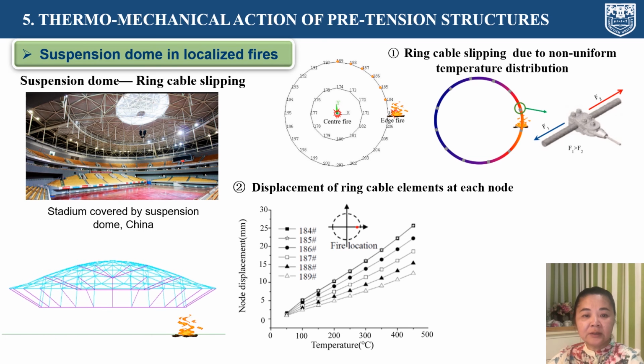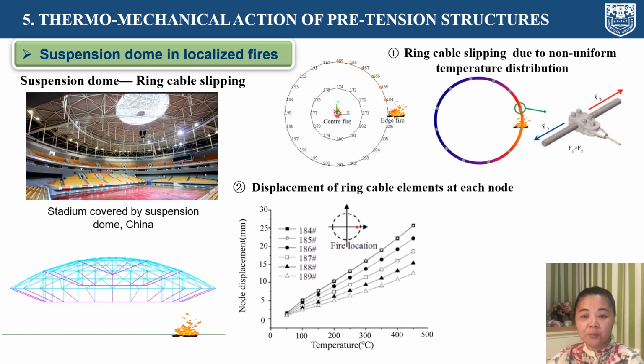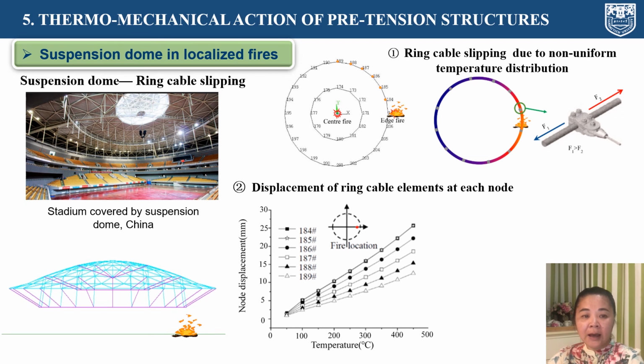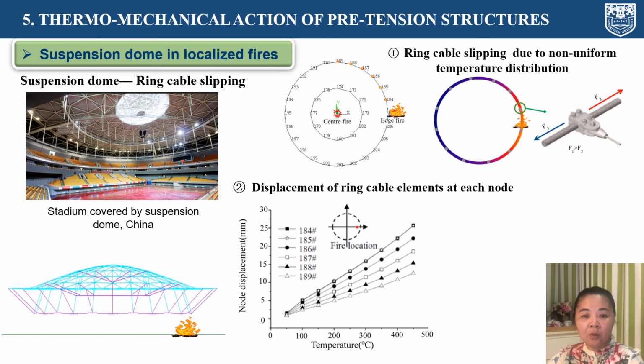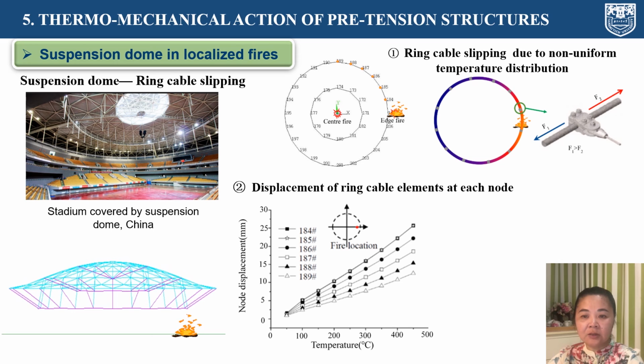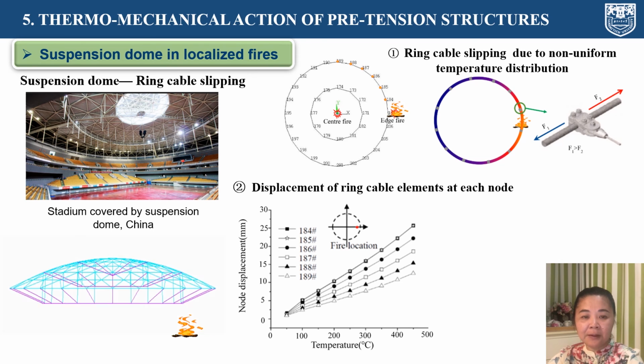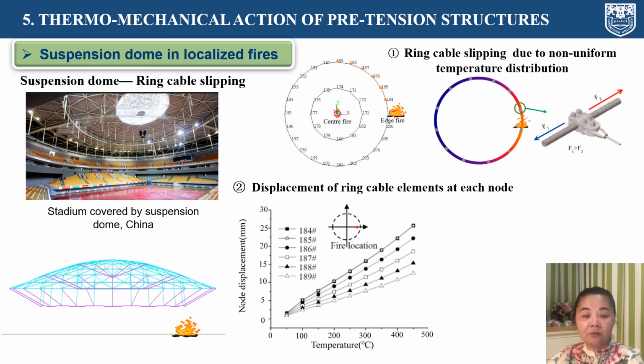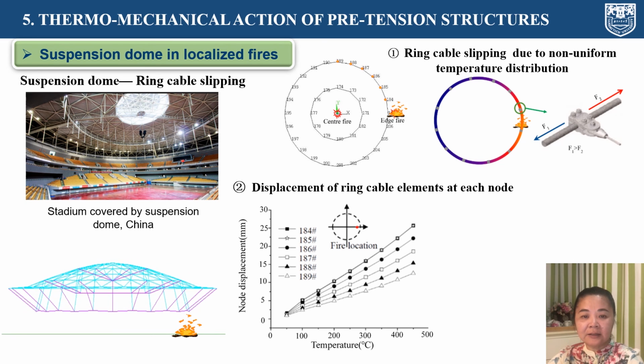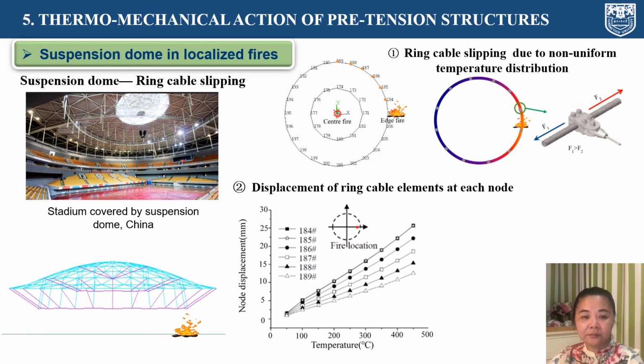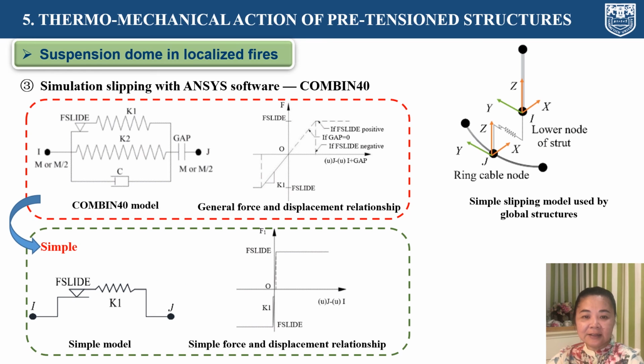Then, when the resultant force overcomes the friction between the surface of the cable and the clamping node, the cable would slip and the pretension force is redistributed just like an elastic band. Slipping action can be discovered by the displacement histories of ring cable elements at each node, as in the figure above. In order to simulate the slipping dependent on slipping resistance using ANSYS software, the combined element was simplified to simulate the joint between a cable and the lower end of the strut.